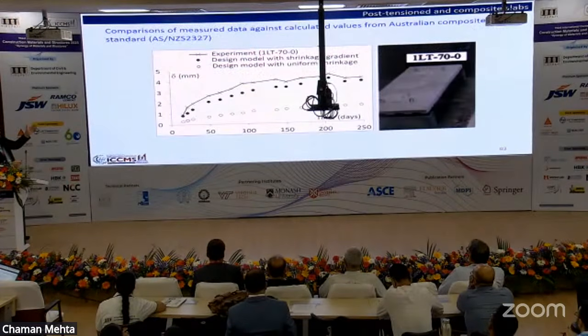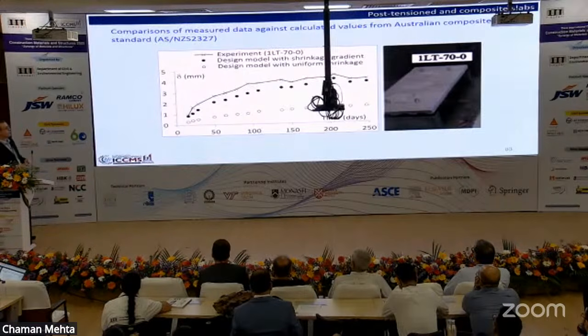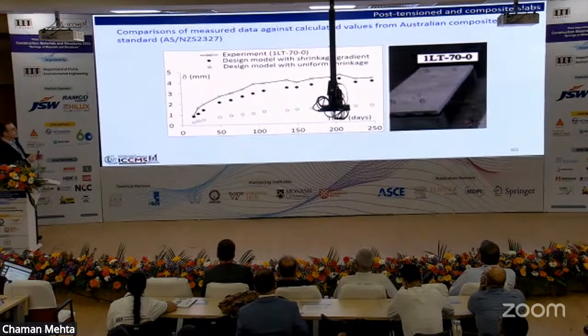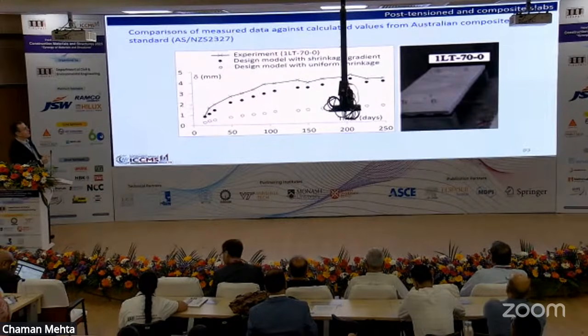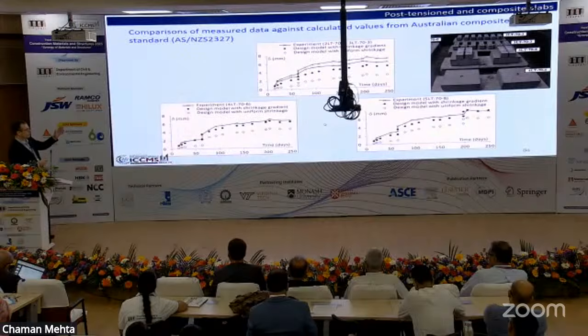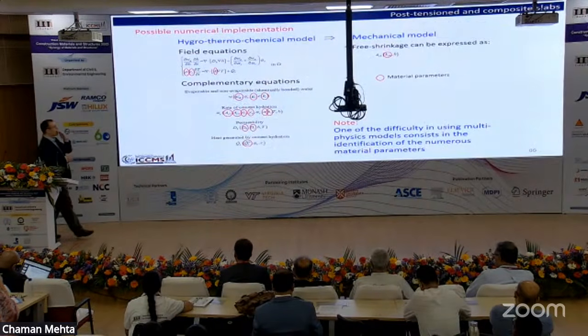So in this case here, for example, these are some comparisons of different tests from elsewhere, not by us. Again, you always have this trend where the experiment has to be really matched only when you have a shrinkage gradient. Without it, you're really underestimating deflections. And this applies to a lot of them. So this is just confirming again for different test results. And this is when you want to push it.